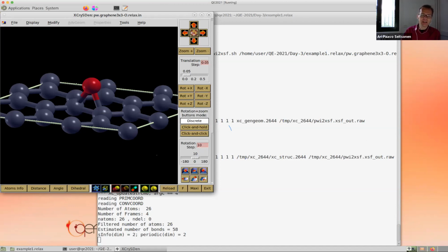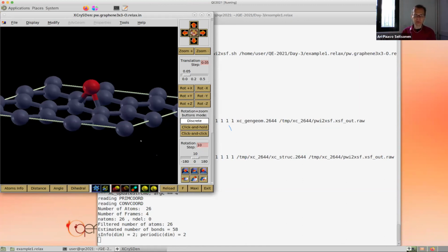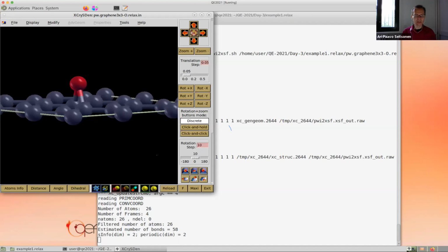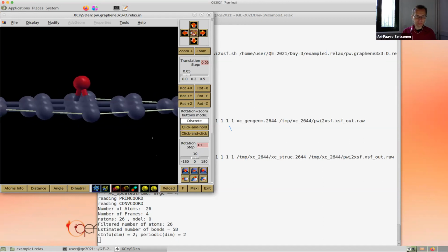it will create a dipole. It will be partially charged, of course, it is more electronegative than the carbons, and so on. So it kind of creates a dipole, and it's partially charged even, so there is this 1/r dependence on the distance between the periodic replicas and so on. Again, this we don't do today, but you should do that if you do a real project. You should be sure that these defects or these adsorbates are far away periodically, that you are converged to some criterion. I don't know, some 10 millielectron volt interaction between the periodic replicas.